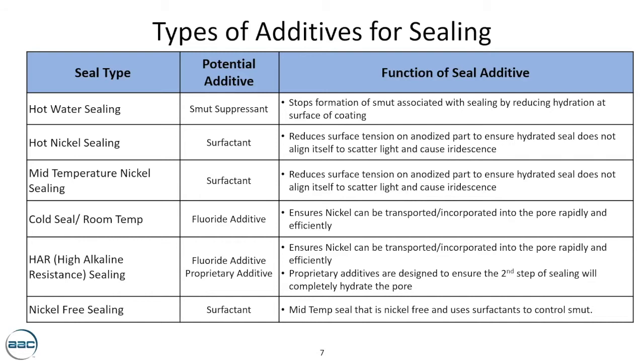In the case of the mid-temp, the surfactant life is a little bit longer, and so mid-temps have become a little bit popular because you can seal and get a good quality seal with a much shorter immersion time than you would with hot nickel, and the surfactant can hold up to lower temperatures, in this case 170 degrees. But the battle you will always be fighting with these two types of sealing is managing that surfactant, and if it is being depleted disproportionately, how do you incorporate that surfactant into the chemistry to ensure you're getting parts that don't have smut on them?